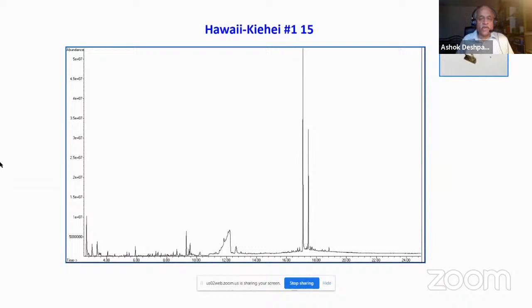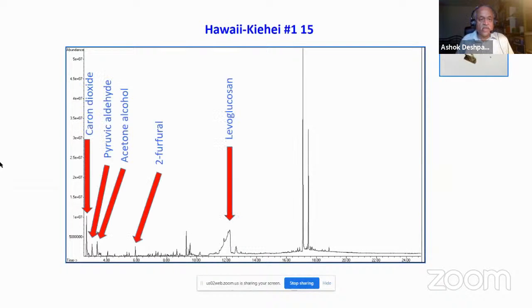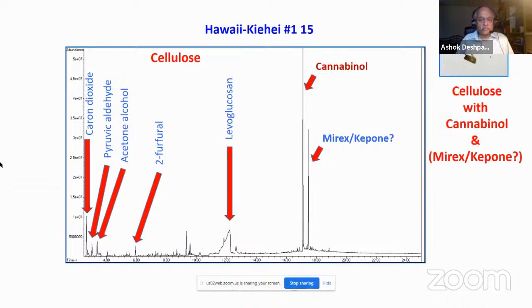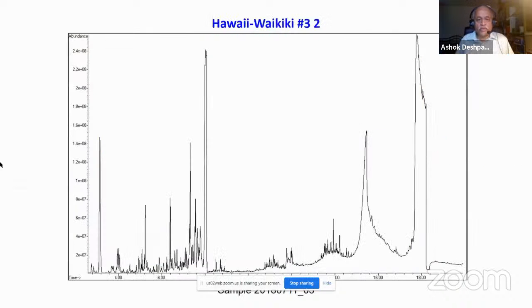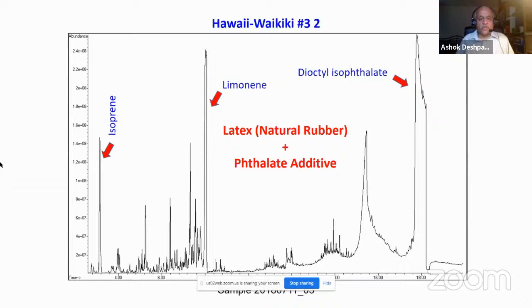This sample from Hawaii was interesting. It showed signature of cellulose. In addition, it had a peak of cannabinol, and it also had a peak for Mirex/Kepone. Next sample contained isoprene and limonene, and also an additive called phthalate. So we called it latex plus phthalate additive.